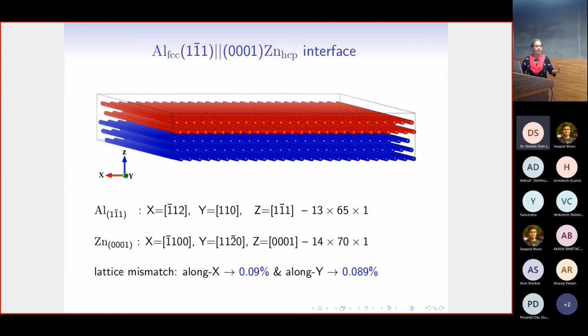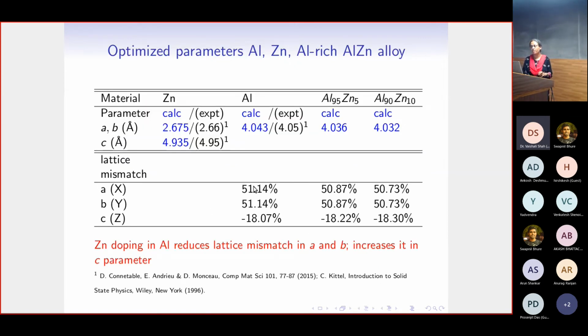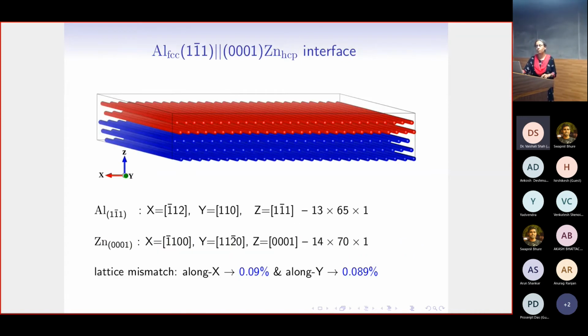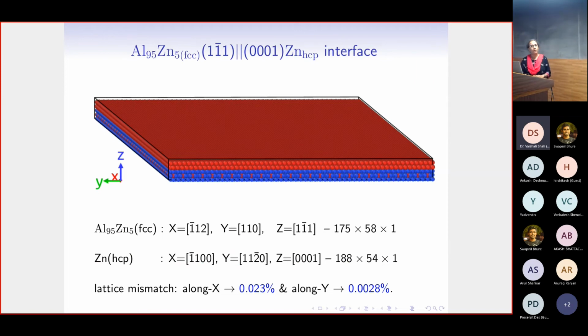So now this is a large unit cell, let me say, that we have to work with to be able to get such a small mismatch along the X and the Y direction. Because if we look at what is the original mismatch, it is 51% in the A and B direction. So by repeating that one single cell structure many times, we are able to reduce that lattice mismatch and bring it to 0.09%. Now similarly, we did this for the aluminum 95 zinc 5 and the aluminum 90 zinc 10. I'm just going to show you the result for the 95 zinc 5